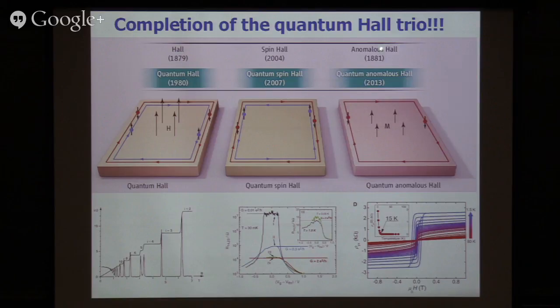But then, in addition to these two Hall effects, there's also the spin Hall effect. In this case, it's a spin-orbit coupled material respecting time reversal symmetry. So when you pass a current in this direction, you're not allowed by symmetry to have a voltage, a charge imbalance, but you can actually have a spin imbalance on both sides. And that effect was also experimentally observed. But now, interestingly, to each one of these three classical Hall effects, there's a quantum version.